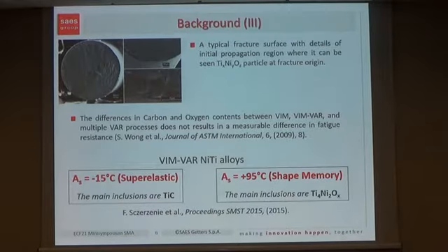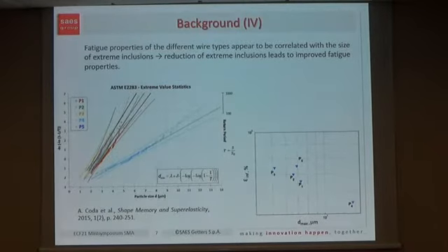Our hybrid VIM-VAR approach on nickel titanium productions brought to the conclusion that in standard superelastic alloys used in biomedical applications the main inclusions are represented by titanium carbides. This doesn't mean that intermetallic oxides are completely absent. While on the other hand, in shape memory materials with an A_f transformation temperature above 95, the main inclusions are intermetallic oxides. Our work in understanding the effects of inclusions on fatigue was focused on superelastic wires, and these are the main conclusions.